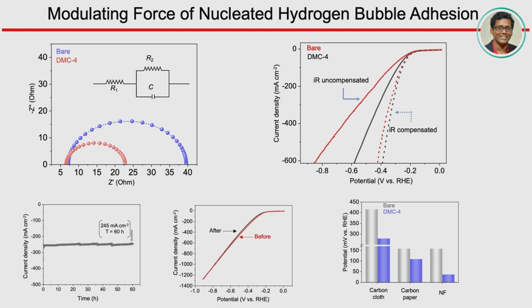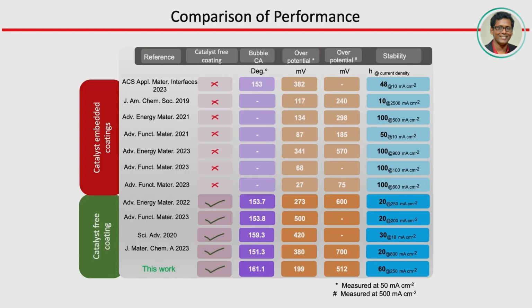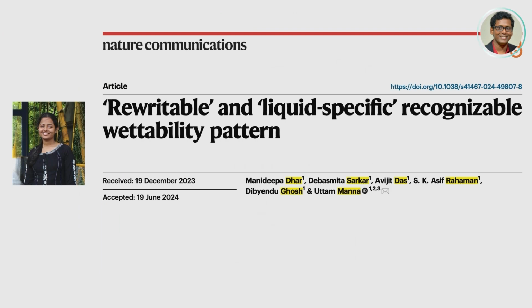It also doesn't depend on the nature of the electrodes. You can also use carbon cloth or carbon paper, and you see a similar tendency. Not only that, if you see this comparison table, in the literature mostly people go with catalyst-embedded coatings, and this is a catalyst-free coating. This approach of controlling adhesion and bubble wettability really helps us improve performance with respect to overpotential as well as stability. So with that, I'll go to the next story, the last story.